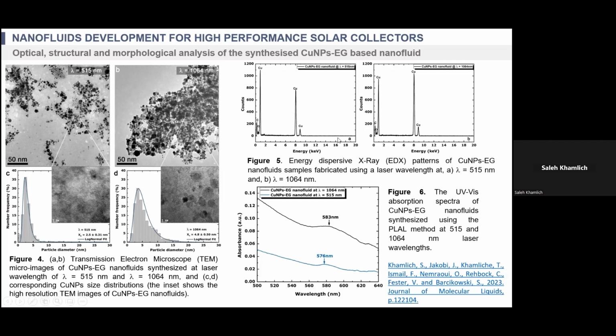By looking at the elements, to make sure that we have copper, this is what we call the energy dispersive X-ray patterns. This shows clearly that we have copper there. The carbon is coming from the grid used, because it's coated with carbon, and there is a little oxygen there. This doesn't mean that we have an oxide there. It could be a small layer of oxide which we couldn't detect. Maybe we have to look for other techniques in order to make sure that the surface is not oxidized. But even so, the oxygen peak there is really very narrow. So this proves that we managed to produce nanoparticles to create what we call ethylene glycol nanofluid.